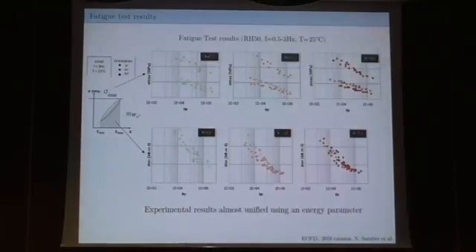If you look at the results, you can have different types of representation of your SN data. So you can use standard stress-based approach. You will see that you have a large deviation between 0-degree specimens and 90 and 45-degree specimens. And what we are developing at the lab, it's more energy-based criteria. And if you do that, you will see that you will more easily unify your fatigue data. So you say, okay, it's much better, I can have a criteria that unify my experimental results.